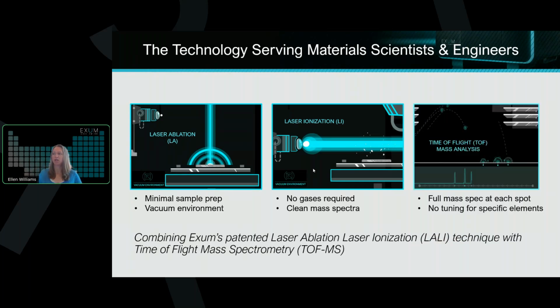Once we have all those ions, we hit them all with the same amount of force and send them to our time of flight mass analyzer. What this does is it measures the difference in times that it takes for ions of different masses to impact that detector. The advantage here is that we get a full mass spectrum, everything from lithium to uranium, at every single one of those laser spots. That means we don't need to be looking or tuning for certain materials.